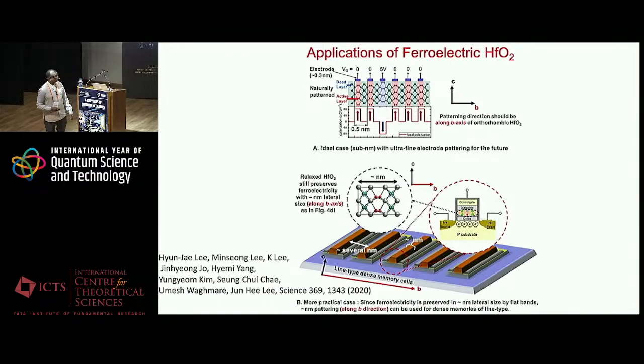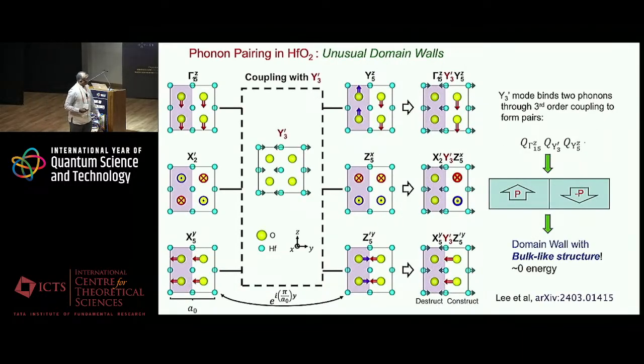And later, basically, what we have shown is there is phonon pairing in this material. The physics of this ferroelectricity is very fascinating. These two phonons, polar and antipolar phonons, are coupled by this zone boundary phonon vibrational mode. And once they couple, you get basically this pattern. And there are 3 pairs of phonons at least which are involved in this phase transition, which means there are 6 component order parameters, but they're very special because they involve pairing of phonons, like pairing of Cooper pairs in some sense. In this case, the mediated interaction is by another phonon.